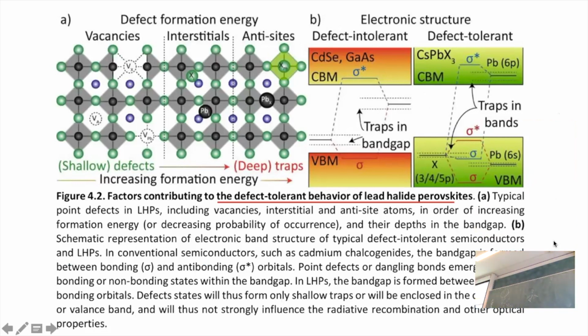So here we have such a lattice. We have all these octahedra of the perovskite. They are nicely connected. We have a lot of them, but we have a vacancy. This here is a lead vacancy. So you see that there should be a lead atom, but it's not there. So this is a defect. This here is a defect of the A cation, like the formamidinium. This here is a defect of the halogen. So if you have a crystal and just an atom is missing, and this can happen, then you have a defect, so you can lose charges there.